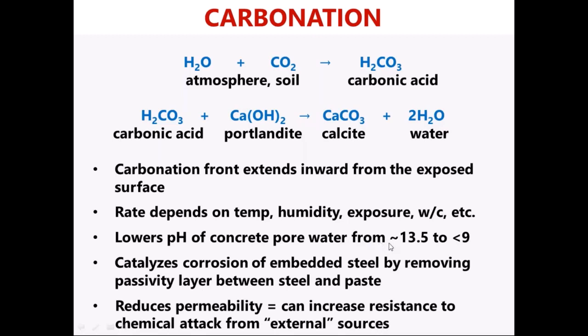The problem, though, is that when you carbonate the paste, if that carbonation front extends down to where there are embedded steel items, the lowered pH of the paste removes the protective passivity layer that's surrounding the steel, and therefore the steel will start to oxidize, it will rust and corrode, and that itself will cause byproducts that expand and crack the concrete. So carbonation is a double-edged sword. It's both good and bad.